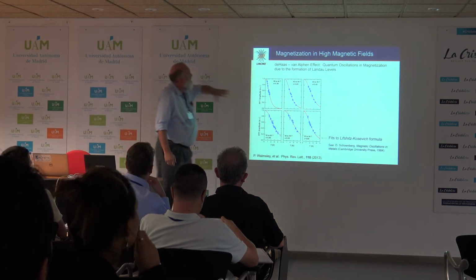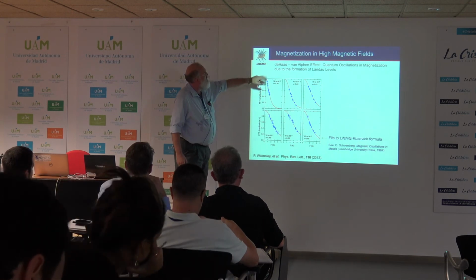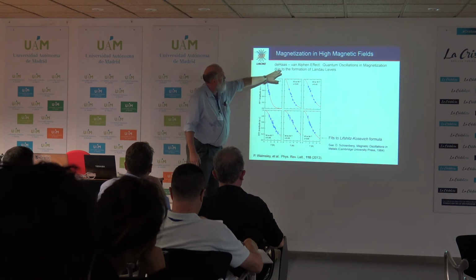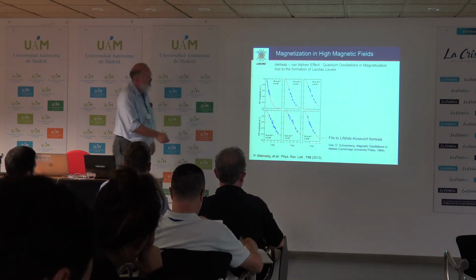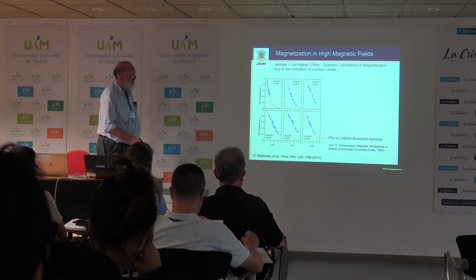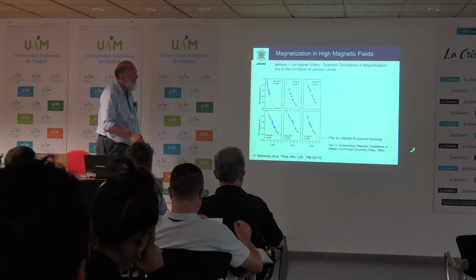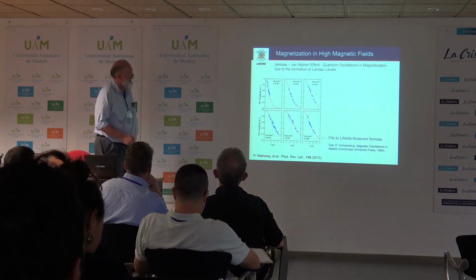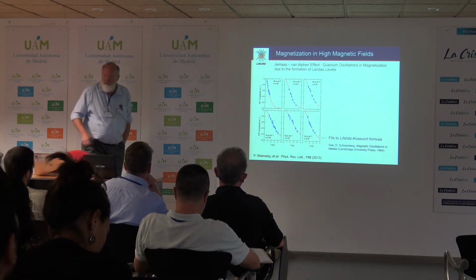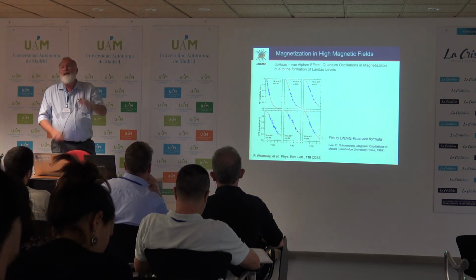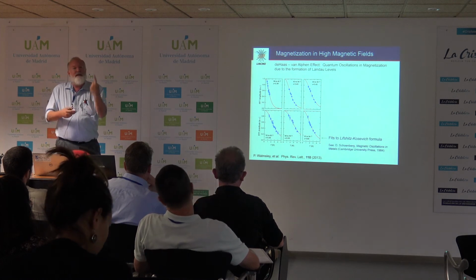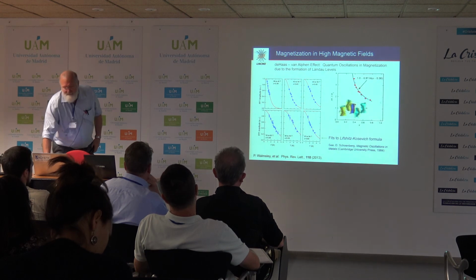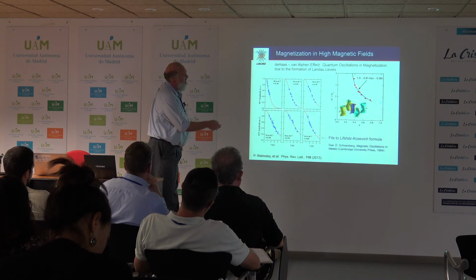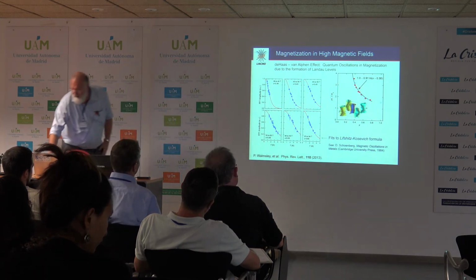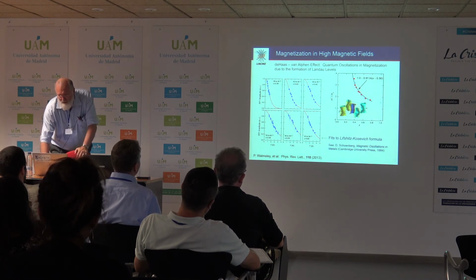And then in high magnetic fields, they take the same system, they measure quantum oscillations in magnetization at the Magnet Lab in Toulouse, and these quantum oscillations arise from the formation of Landau levels. They fit to the standard formula, which is a transform of the Fermi-Dirac statistics. If you'd like to learn about quantum oscillations, this is the Bible still, Shoenberg, 1984, Magnetic Oscillations in Metals. But this temperature dependence of the amplitude of the oscillations as a function of different dopings here gives them the mass from quantum oscillations from the one pocket that's showing the quantum oscillations. So here they've got the resolution to nail down the mass divergence from a single pocket. And they see this clear enhancement in the mass as you approach 0.3. And they're taking this data up to 60 Tesla because you can do quantum oscillations in a pulse magnet.